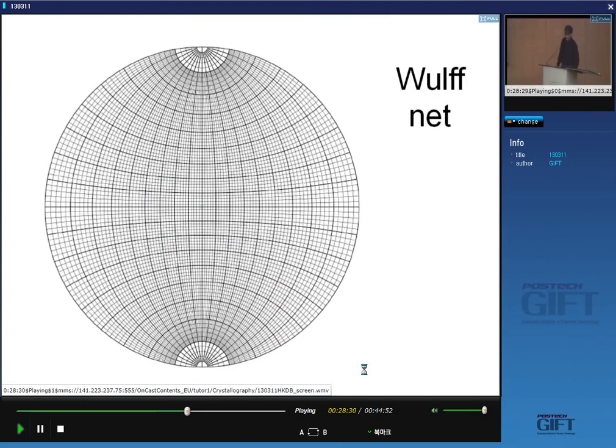Now, I mentioned to you that when we make projections, there will be distortions, because we are taking a three-dimensional object, in this case a sphere, and projecting it onto two dimensions. So it's difficult to measure angles, because on a stereographic projection, there are angles between two points. It's an angular projection. So we can calculate all those angles, and this is what we call a Wulff net. It's like a ruler for measuring angles. Supposing I have two points here and here, then I can count 2, 4, 6, 8, 10 degrees between those two points.